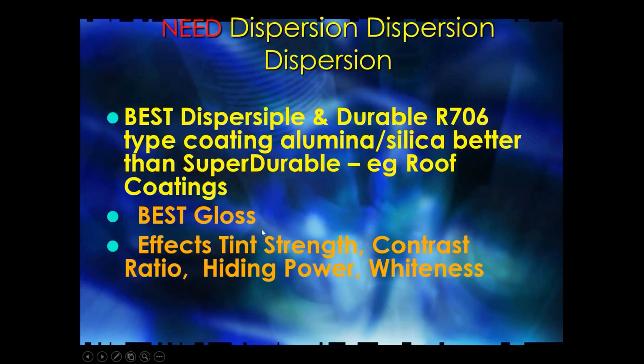So we're concerned about dispersion because we get the best possible gloss, and then we dumb down the gloss with other additives like silicas and clays. The dispersion affects the tinting strength, the contrast ratio, hiding power, and whiteness. Now, the whiteness of the product is determined mostly by the impurities, but if the particle size is just slightly too big, bigger than a quarter micron, then it will begin to bend the light and you'll have kind of a yellowish characteristic to this.